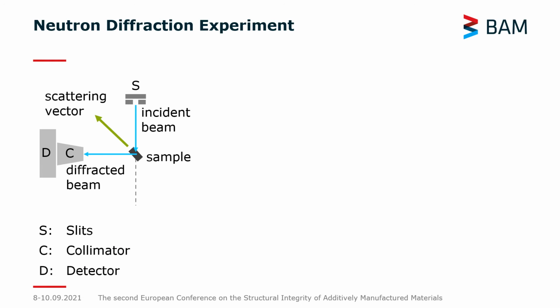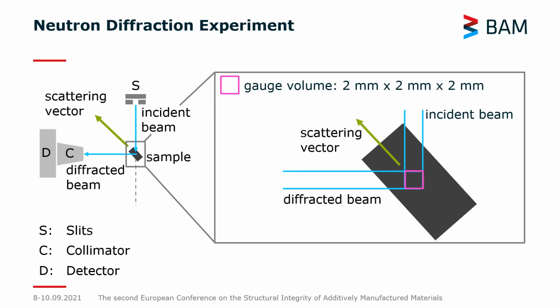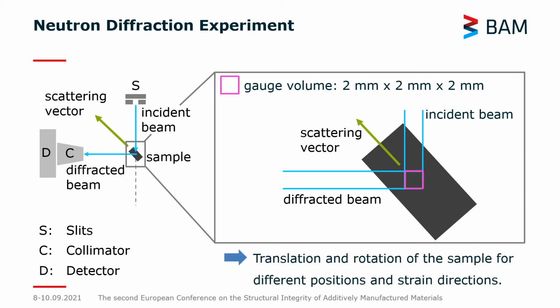Now, how does it look during a neutron diffraction experiment? We use a set of slits and collimators to define our gauge volume. Thereby, we will determine the strain along the scattering vector, which is the bisectant between the incident beam and the diffracted beam. If we zoom in, the gauge volume used for this study was 2 by 2 by 2 millimeters. You see our gauge volume inside of the specimen with the direction of the scattering vector. And what it basically means, thinking back about the methodology of neutron diffraction, is that we have to translate and rotate our sample so that we acquire the stresses in different positions.